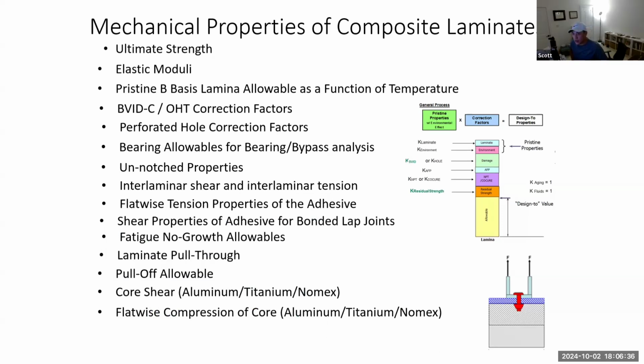I don't know exact details, but just from a high level perspective, the matrix is a pre-preg matrix. It gets cured, right? So it's a thermoset matrix. It turns into a plastic type of substance. But under high temperatures, that matrix starts to degrade and starts turning into more of a liquid. Once that starts to degrade, you start to lose the bonding between the plies, and the overall strength of your laminate will decrease. So typically they do testing of laminates under various temperature zones. This is something you need to validate through test. You can't just figure this out analytically because it's a material property type of check.